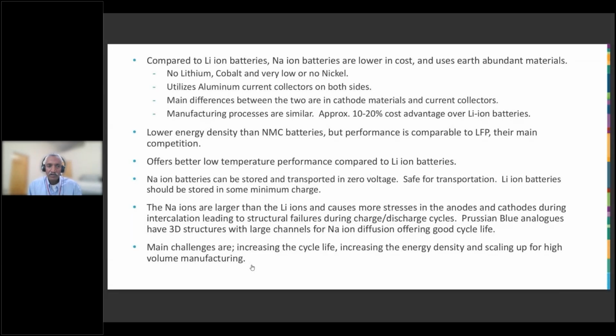They have a lower energy density compared to NMC batteries, but the performance is comparable to LFP batteries, which is their main competition. They offer better low temperature performance compared to lithium-ion batteries, and they can be stored and transported in 0-volt state, so it's much safer for transportation. Whereas lithium-ion batteries, you always have to store under some minimum charge.